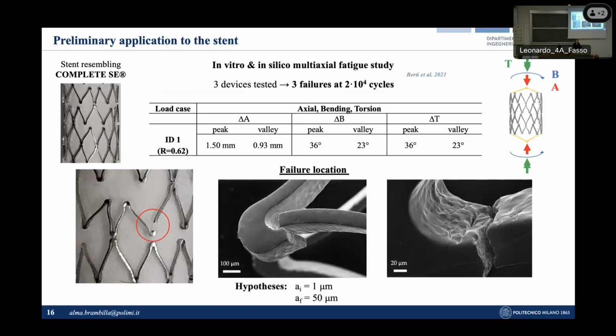And also in this case, after the test, the fracture surfaces of the stent were inspected through a scanning electron microscope, highlighting the presence of an initial defect with a size of approximately 1 micron and a crack propagation length of about 50 microns.